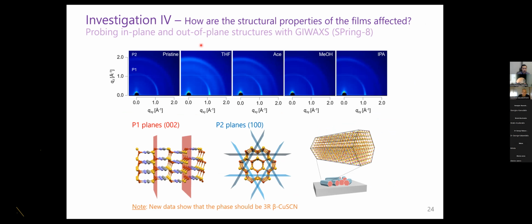And when we looked at the structural properties, we find that the thin films became more crystalline compared to the pristine state.